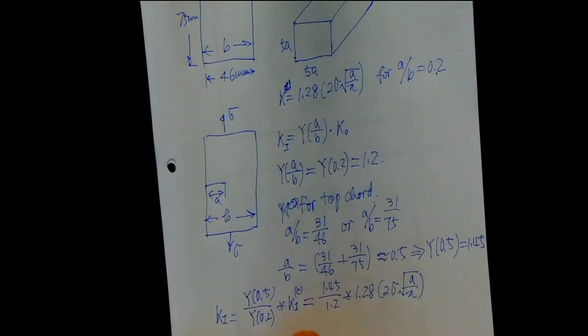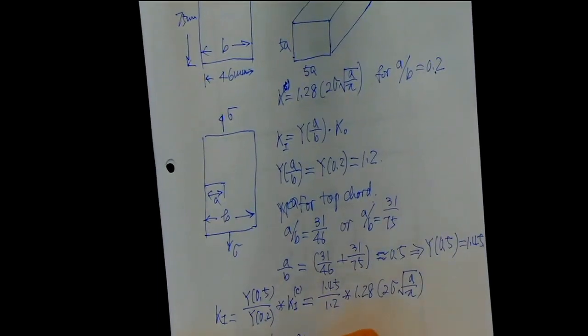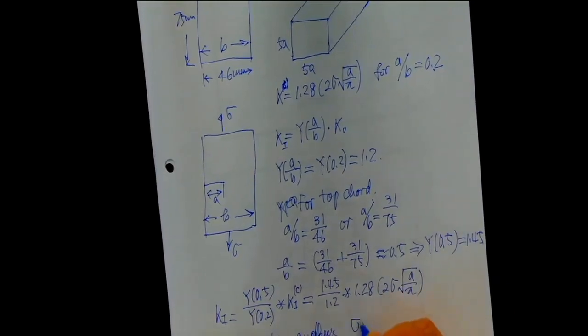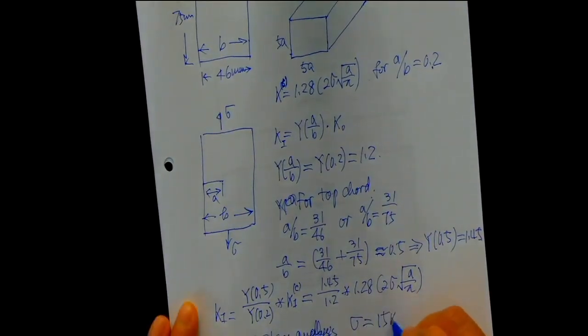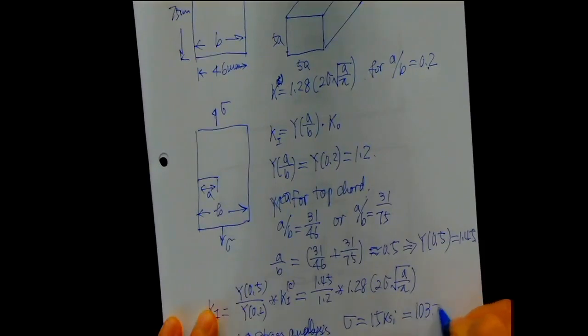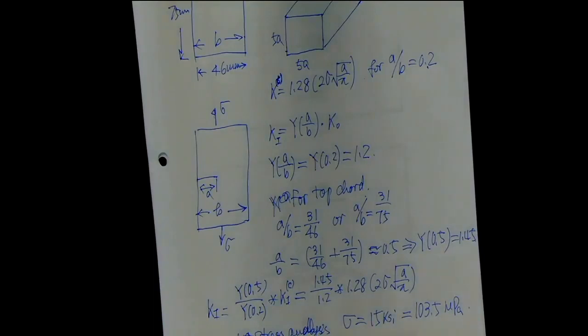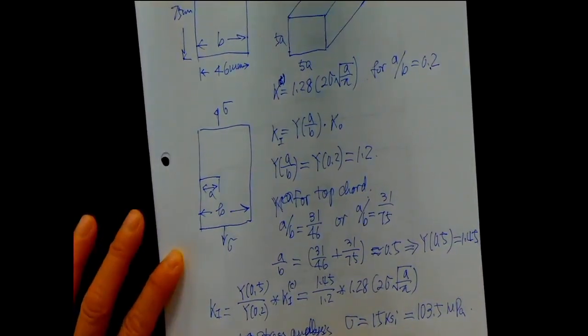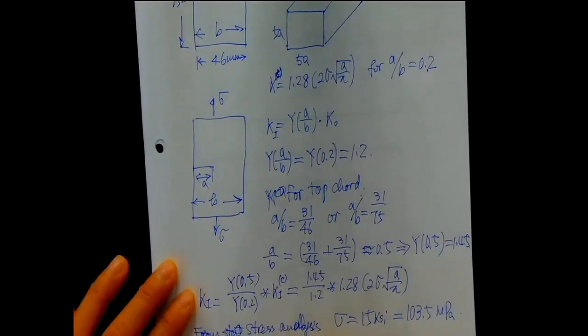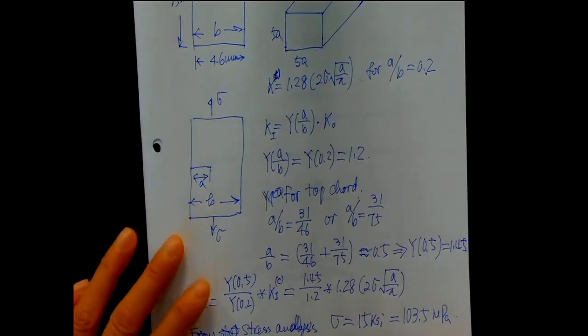Okay, so from the static analysis or stress analysis, the sigma is equal to 15 KSI, which is 103 megapascal. So if you plug all of those into that number, you find K1 is equal to, you plug all those in, so it's 1.45 times, and what you get is 31.56.